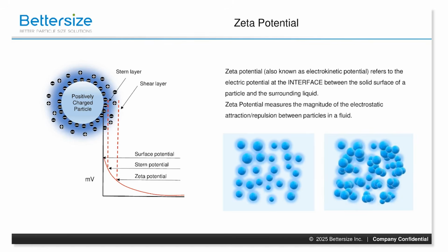Particle concentration can lead to particle-particle interactions, which can affect the overall zeta potential. The presence of surfactants, polymers, and solvent properties matter too. And surface modification of the particle with coating or functionalization can alter the surface charge and thus the zeta potential.